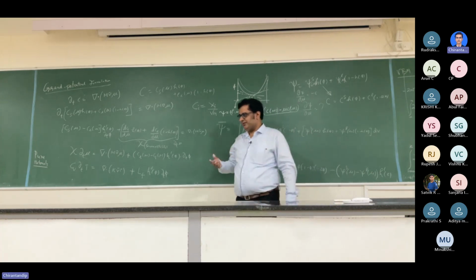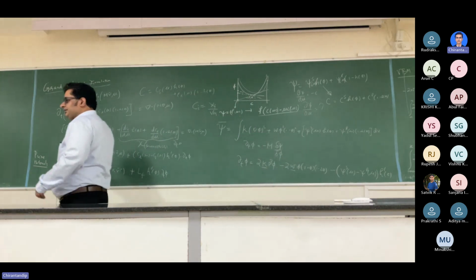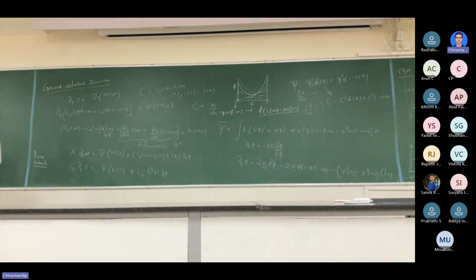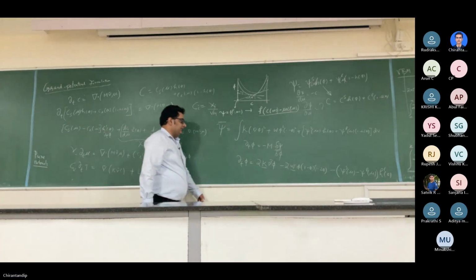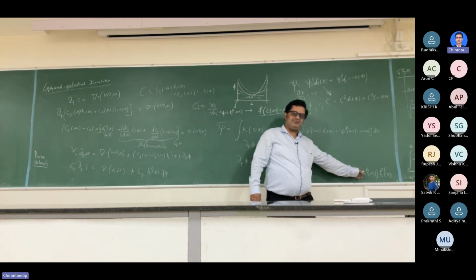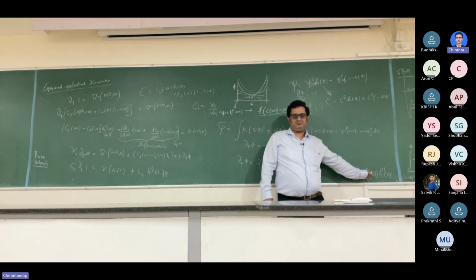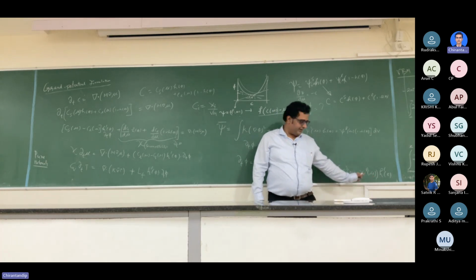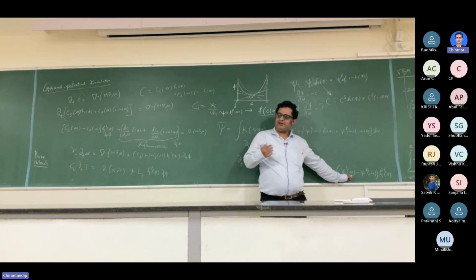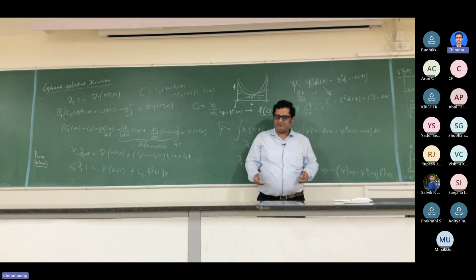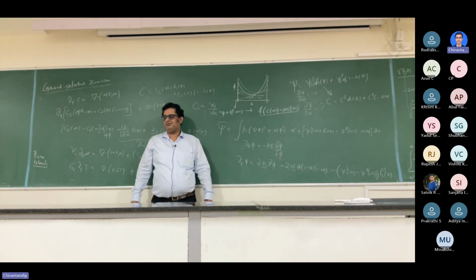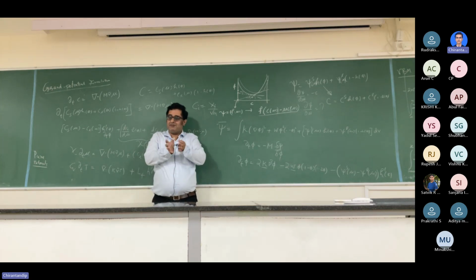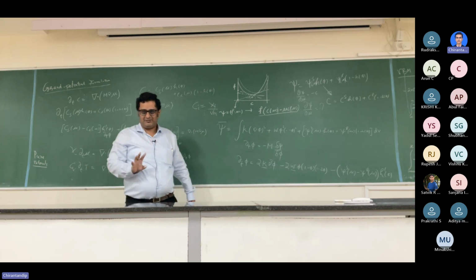In the case of pure materials, the grand potential and the free energy are interchangeable because for a single component, G by N is directly mu. Because of that, for the pure material case, Fs minus Fl is directly the pressure difference there as well. And thereby, a driving force having a direct connotation with pressure makes perfect sense thermodynamically, and it's not a surprise that you will do this. So the beauty of physics is that all things fall in place at the same time if everything is right. That's essentially what I mean.